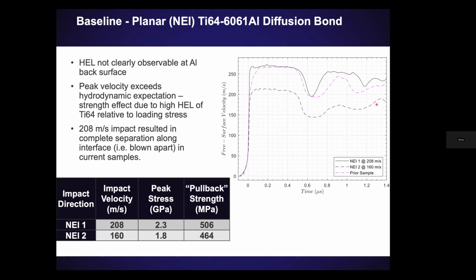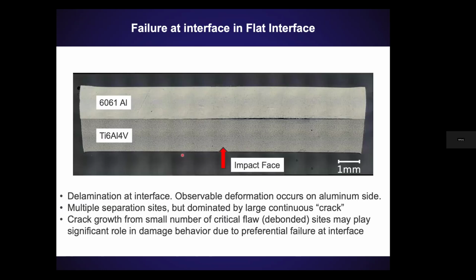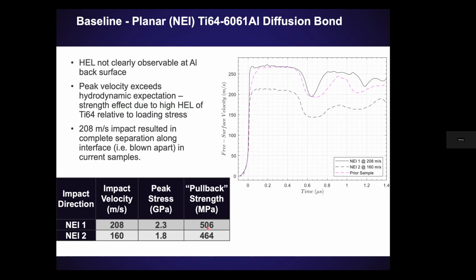And that's why you see this type of velocity time profile. And really, it is really hard to get from these. You could take this difference and say that's your pullback strength. And because we were failing at the interface, we could call it the strength of the interface, essentially. And we could see that, okay, this is my flat interface, there's a difference. If I take the same flat interface and shock it multiple times, there is some variability in what you would call spall strength of that interface.